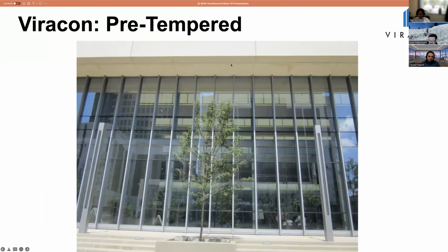So this is a project in Ohio that Viracon did. I believe it's a VRE 54. Viracon was spec'd and sold the job, and it was put up. When you look at roller wave distortion, or distortion in general, the only way you can tell it's distorted is if you have an image in the reflection. So in other words, if we put a building on top of a hill and the only thing you're seeing is sky, it could be the most distorted glass in the world and you'll never know it because you don't have anything in reflection. So in this photograph, you can see in reflection the building behind, and you can see how relatively straight those lines are.